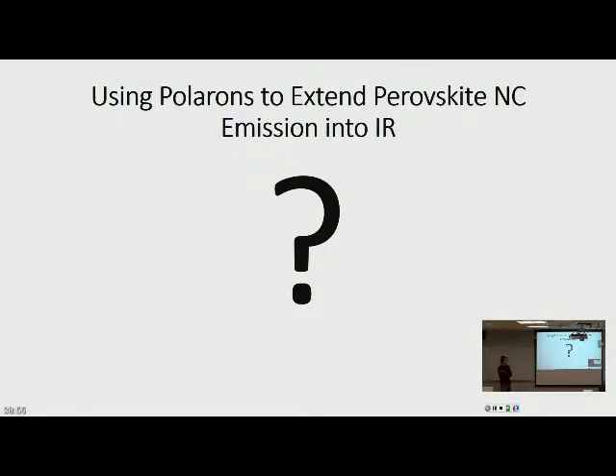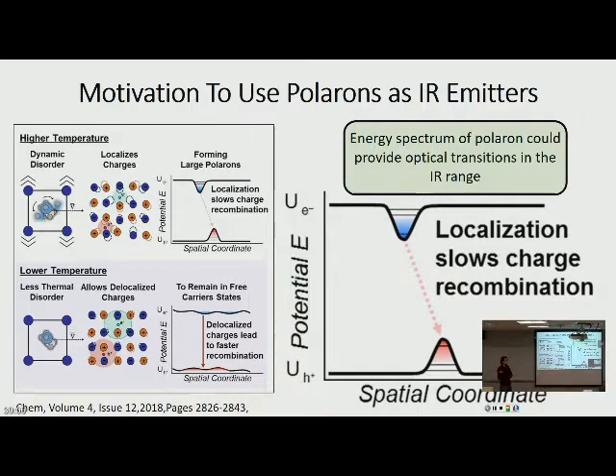And then what we're focusing on is whether we can use polarons that form in these nanocrystals to get IR emission in these states. I didn't put a lot of information on polaron background, because I did that in my last talk. But I guess the basic idea is, if you look at this paper, you have a neutral state, then you photoexcite it. You have positive and negative charges in your lattice now. And since perovskites are ionic, they interact with those excess charges, and then they move around. They just kind of screen the charge.